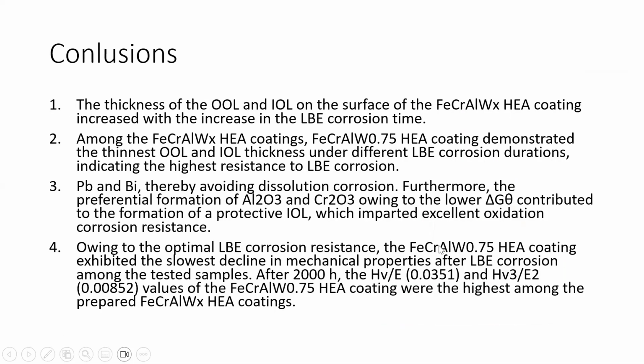protective mechanism. So the conclusion from this paper is: one, the thickness of the outer and inner oxide layers on the surface of the ferrochromium alloy tungsten-x coating increases with the increase of LBE corrosion time. Among the ferrochromium alloy tungsten-x coatings, the tungsten 0.75 coating demonstrates the thinnest outer and inner oxide layers under the same LBE corrosion duration, indicating the highest resistance to LBE corrosion, thereby avoiding dissolution corrosion.